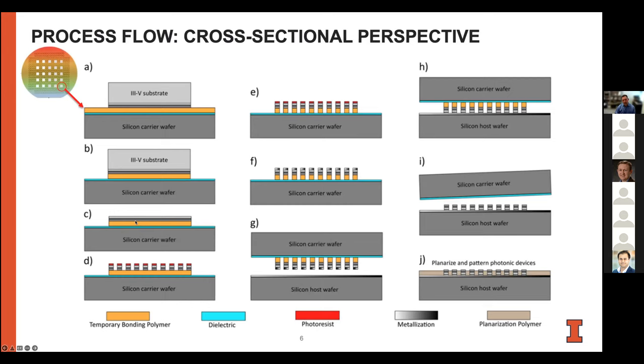Then in a wafer scale process, we can pattern where those islands are located. So the initial process here can be done very coarsely, basically even hand placing the 3-5 material on our carrier wafer, although we envision ultimately using something like a pick and place process to do that. And then when we photolithographically define the islands by depositing a hard mask, patterning that photolithographically, we now have islands